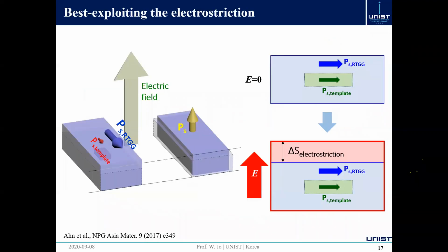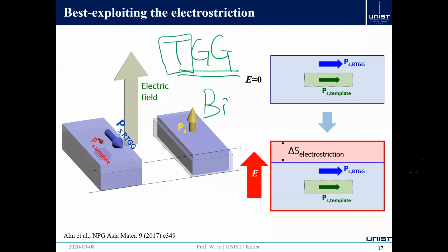So the idea was simple. We utilized the templated grain growth technique, but the difference between typical templated grain growth and ours is the type of templates. Instead of using normal templates, we use a polarizable template, which in this case is a BiT particle, a ferroelectric with a polarization along the a and b crystallographic directions. That means the Curie temperature of this BiT particle is a lot higher than usual ferroelectric lead-free piezoelectrics.